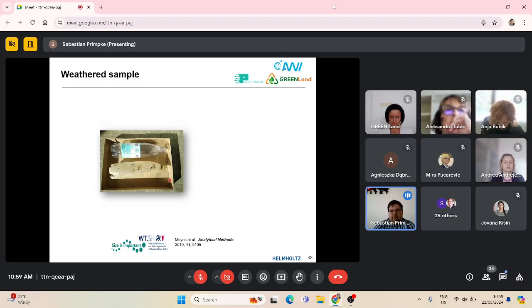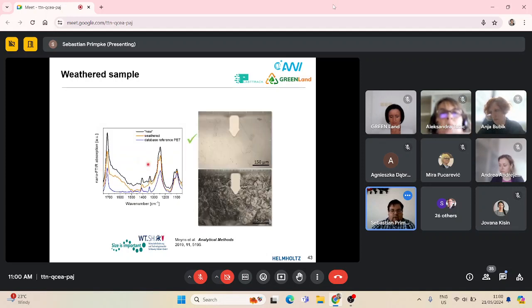You see here the unweathered material and the weathered material, and as we heard already today, the surface properties are extremely important. You see it's cracked, and I think we already lost a lot of small particles. But if we look at the spectra, they look more or less the same, even on this small nanometer scale, between the weathered material in orange and the new material in black. You see more or less every signal is present. There could be one turning up, but as the laser is limited, we could not measure further down. Still, it shows that it's quite important.